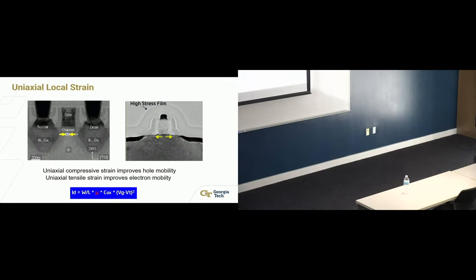Because if you look at an introductory textbook, we tell you about holes, the valence band of holes, and we talk about light holes and heavy holes that we kind of brush aside, but that was where the physics was. As soon as you turn on a uniaxial compressive strain, you lift the degeneracy between light hole and heavy hole and make heavy hole light hole-like, and that lowers the effective mass and actually increases the hole mobility.